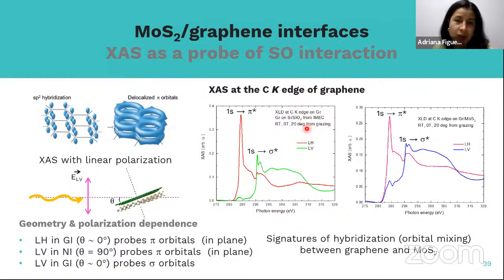The graphene without the MoS2 and the graphene with MoS2. And we observe changes in the spectra that are relevant and that are signatures of hybridization, which means orbital mixing between the graphene and the MoS2.